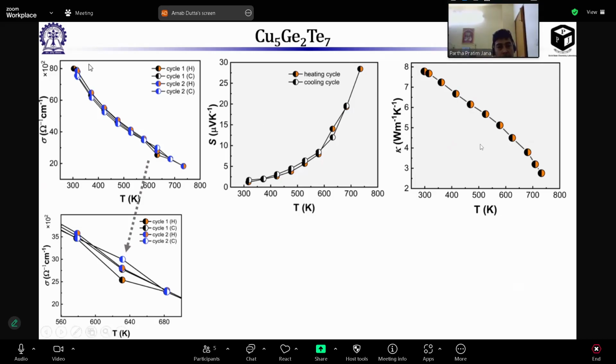From here you can calculate the lattice contribution, and then check whether you really need the CP data or not. So it's ultra low, 8 minus 5.85 at room temperature, so about 2.1. Lattice conductivity is 2.1. That's actually very low.